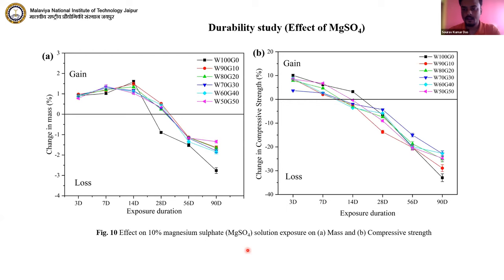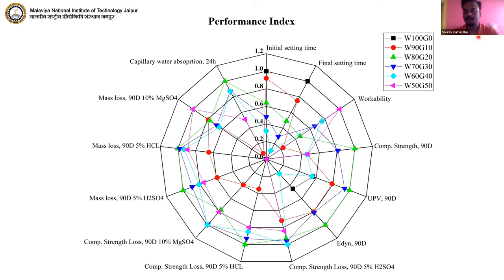And this is the performance index, where I have categorized all the tests on a scale of 0 to 1, where 0 is minimum effect and 1 is the best performance by a particular mixture. Here we have the mixtures and these are the outputs of different test results. On average, the 20% glass waste and 40% glass waste mixtures come out to be the best proportion to be used as a replacement material of waste cement concrete.